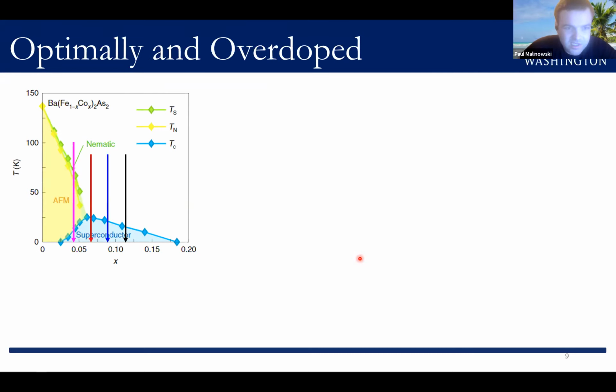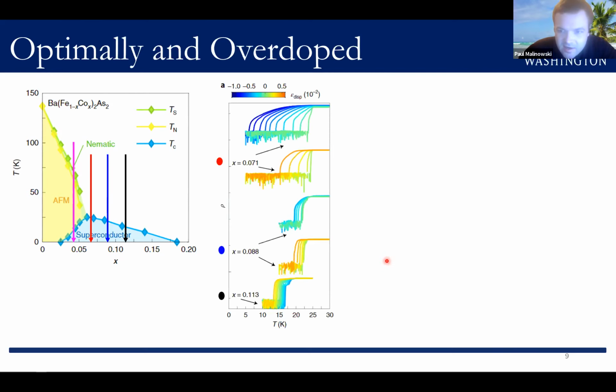But this raises the question of what we'll see in optimally doped and overdoped compositions without long-range magnetic order, because in this case, we expect B2g strain to actually enhance anisotropic spin fluctuations, while at the same time suppressing nematic fluctuations. So here I'm showing the effect of strain on the superconducting transition for the compositions indicated. So you're looking at resistivity on a logarithmic scale as a function of temperature.